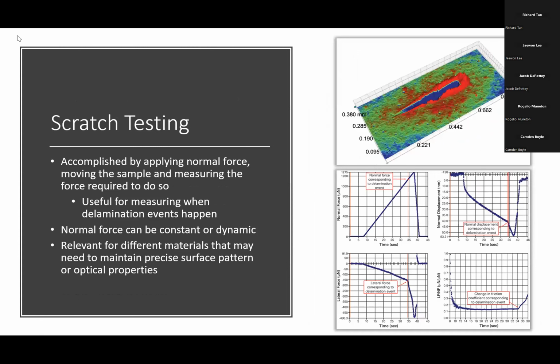Another test for nano indentation is scratch testing. This is accomplished by applying a normal force to your material and moving your sample laterally. The force required to do that movement is what you measure for the scratch test. It's useful for delamination, which is the separation of material parallel to the surface.